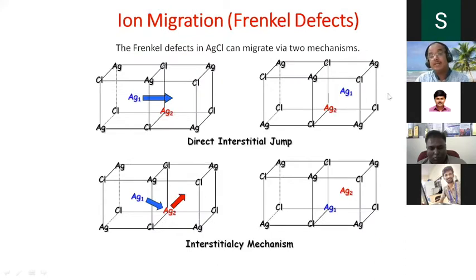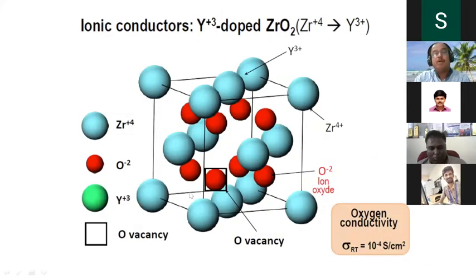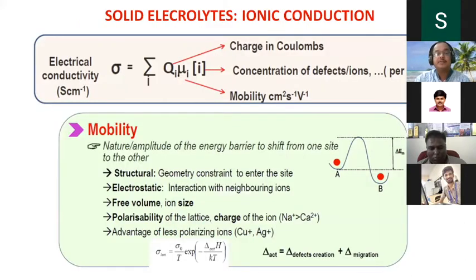Frenkel defects in silver chloride can migrate by two mechanisms, one by direct interstitial jumps and the other by interstitialcy mechanisms. So here silver directly jumps to the silver interstitial. So here it takes this path, not through the lattice sites. So whatever it might be, what you require is vacancy; zirconia is a classic example of the oxide conductors. So vacancy is essential if you really want to think about conduction in this type of solid material. So that is regarding the defects.